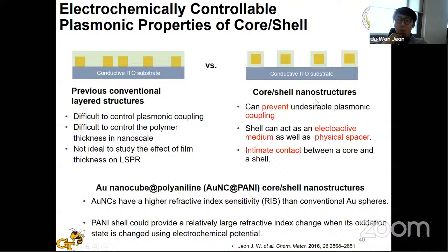But in the case of core-shell nanostructures, the shell can prevent undesirable plasmonic coupling. The shell can also act as an electroactive medium as well as a physical spacer, and provide a different refractive index environment to the gold nanocube. Intimate contact between the core and shell is also guaranteed because the interaction between core and shell is very strong. The reason we use the gold nanocube instead of the nanosphere is its higher refractive index sensitivity than the gold nanosphere.